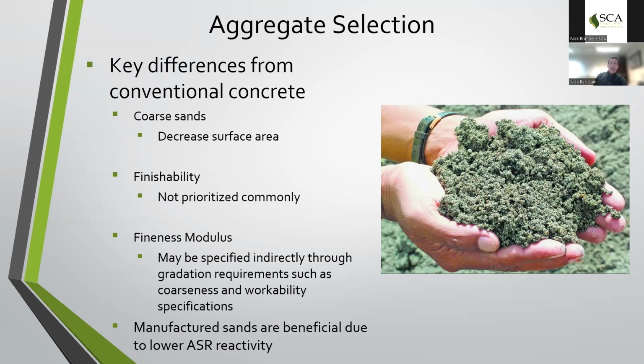One of the downsides of that can be placeability or finishability in certain cases. However, good feedback with aggregate suppliers can always help on that, as they can often make changes both in terms of cleanliness and particle size to help better achieve high pump rates as well as good finish rates. Fineness modulus is a great quick hand way to assess that and then also help with mix design on the gradation side during the production and design process. So short changes can be made to help continue to achieve high levels of quality control.